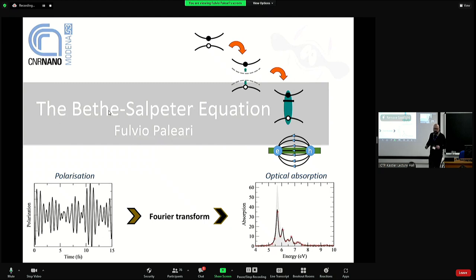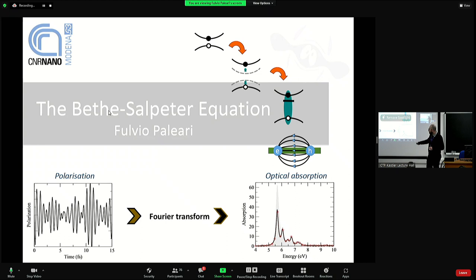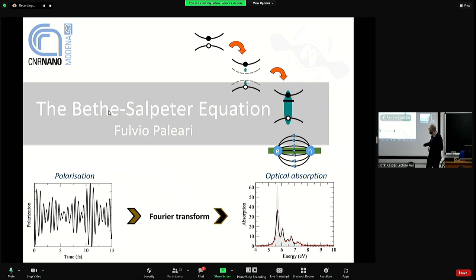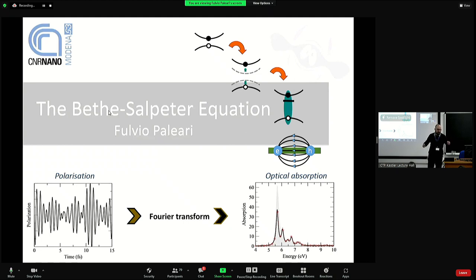When light impinges on a material, a macroscopic polarization rapidly oscillating in time is generated. The absorption spectrum is just the Fourier transform of this polarization, so the frequencies encoded in this polarization end up as peaks in the absorption spectrum. This is also the path we will take for giving a sketch of the derivation of the Bethe-Salpeter equation, which describes electron interactions.